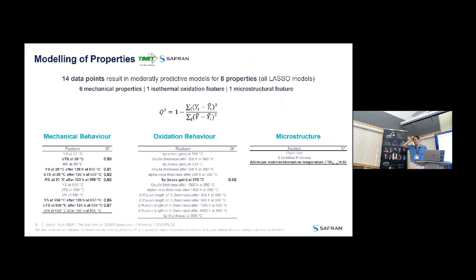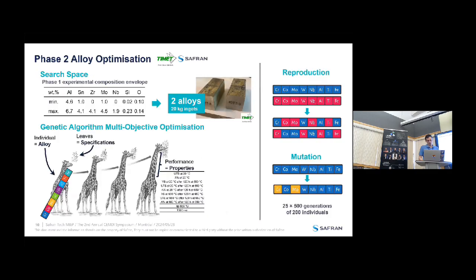So we talked a bit about small data, and the fact that, and we'll come back to that in the conclusion, the materials science data pool. I would say structural alloy design is even poorer because the actual experiments are very expensive. So we tried to build a model using 14 data points. Obviously, it's not a neural network, it's not deep learning, it's just basic linear regression with feature selection in order to simplify the model as much as possible. So the idea is that we got some, I would say, moderately predictive, predictive is a big word there, models for which the Q2, which is kind of a cousin of R2, was sufficiently high for us to believe that the model would guide the design in the correct direction, which is what we did.